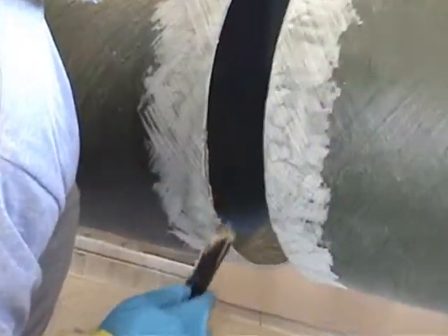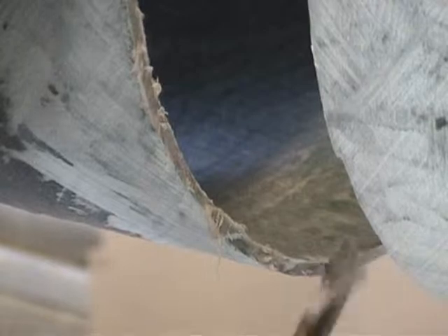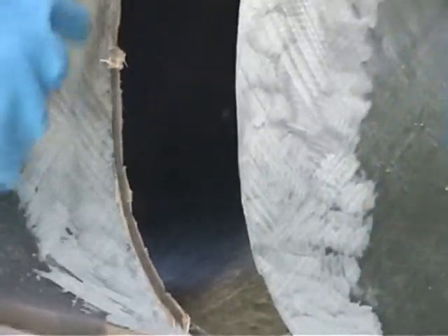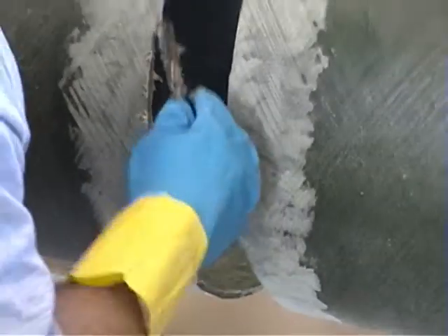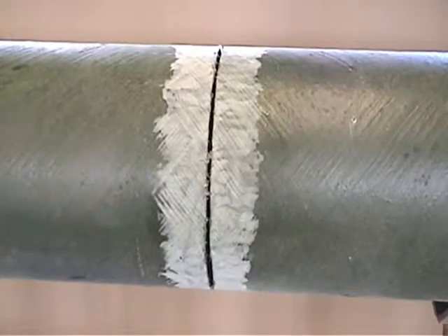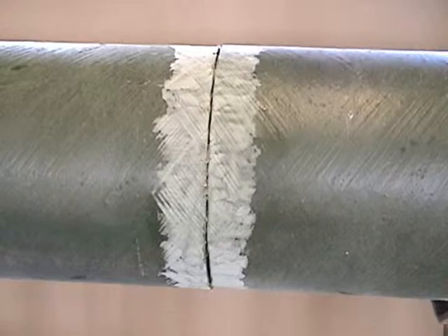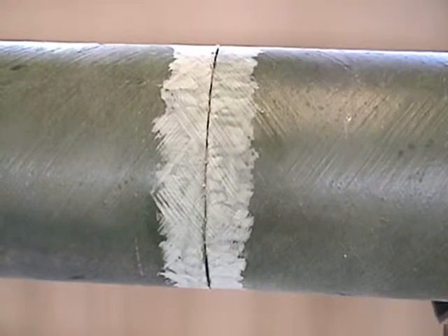It is very important that you always coat the cut ends of the pipe. You can do it either with catalyzed adhesive or catalyzed resin with a paintbrush. This is necessary because there are certain chemicals that can attack the glass. Now that the ends are coated, we butt the pipes together and square them up. Now we're ready to bridge across.